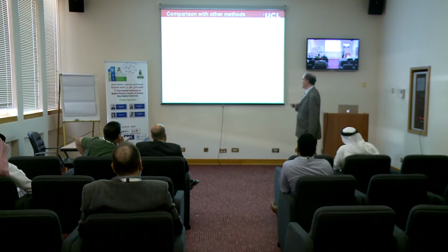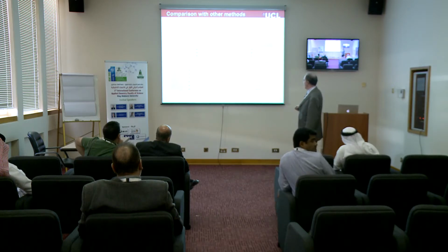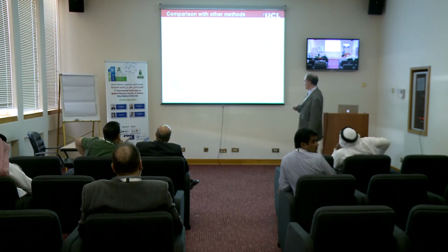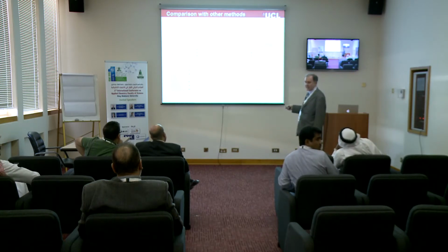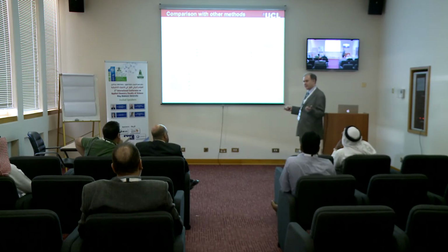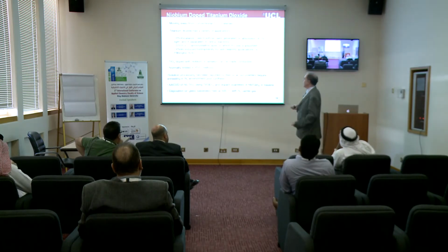So when we compare it with the commercial product, so this is TEC8, which is produced by NSG, and this is Asahi U glass, then we're getting overall better sheet resistances. We get to about 4 to 5 ohms per square, whereas the commercial products are 15 to 28. So we get better transmission, better overall products, and we're looking for commercialisation of this.